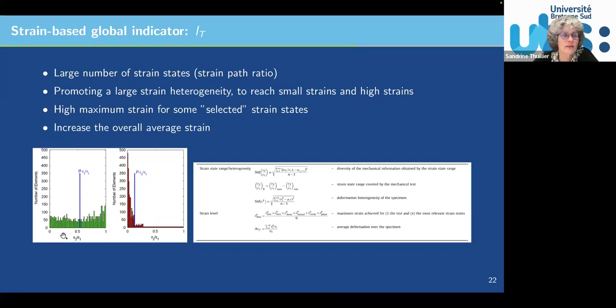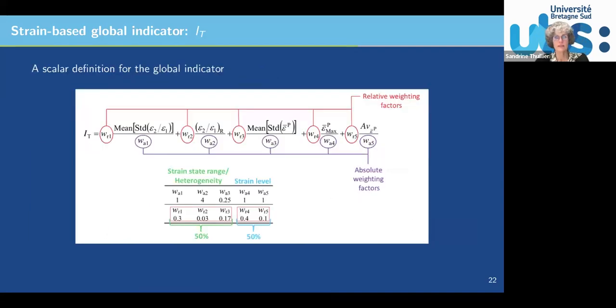If you look here, you've got what we call the strain ratio, the minor strain over the major strain, and you count the number of elements in your numerical model. If you have a distribution like this, I would say your test is very good for heterogeneity, but if it is all centered, this is a kind of homogeneous test. So the idea is to promote this behavior and not this one in order to have rich information. This is the idea of this indicator.